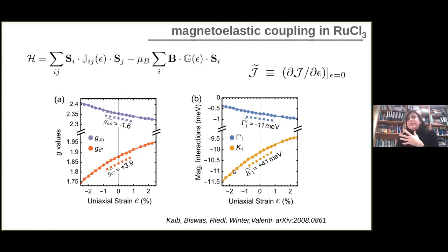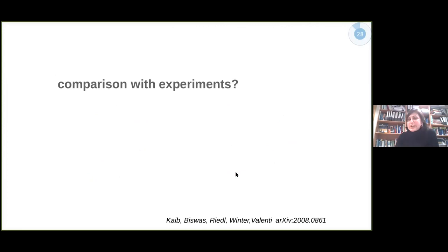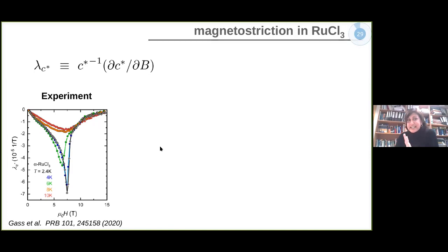Now the question, of course, is this is all simulations. How good are these simulations? So how can we compare with experiment? And this is my last slide. So there is one measurement where we can test these predictions for the changes of our parameters as a function of strain, which is the magnetostriction. So the magnetostriction, what it measures is the changes of your c parameter as a function of magnetic field.